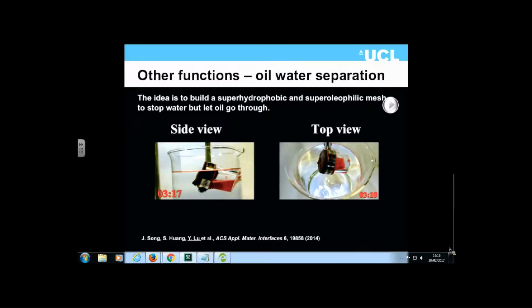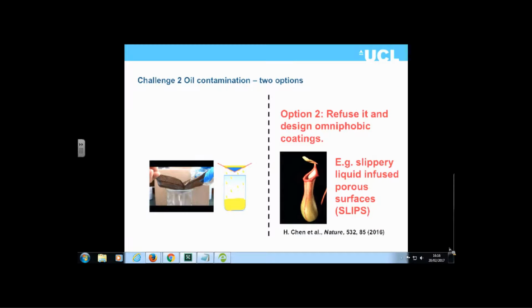After 2 minutes, we've collected all of the oil from this particular beaker, and you can see it's all in the collection jar, showing very clean separation. We can get something like 99.5% or even higher separation using this kind of technology, and also use it to separate liquids from water from a variety of different media, even if they are very coloured.